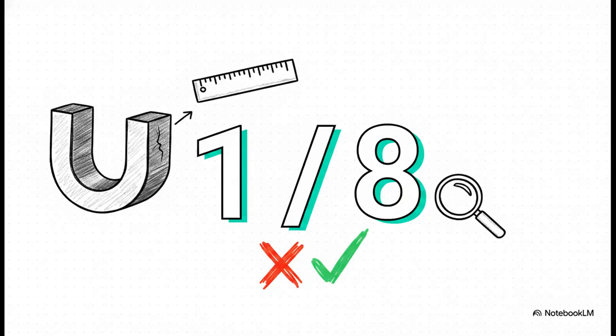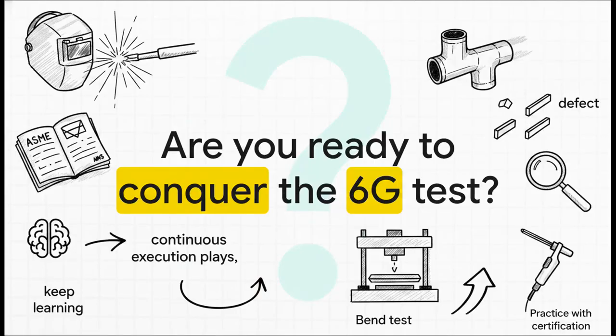1/8 of an inch. Let that number sink in. After your metal has been bent completely into a U-shape, that convex surface is meticulously examined. And for most codes, 1/8 of an inch is the absolute maximum allowable size for any open crack or discontinuity. It is a razor-thin, incredibly tight tolerance for victory. If your crack is even a hair larger than that, you fail, and you have to start the entire grueling process all over again. Which brings us to the end of our chalkboard explainer today.